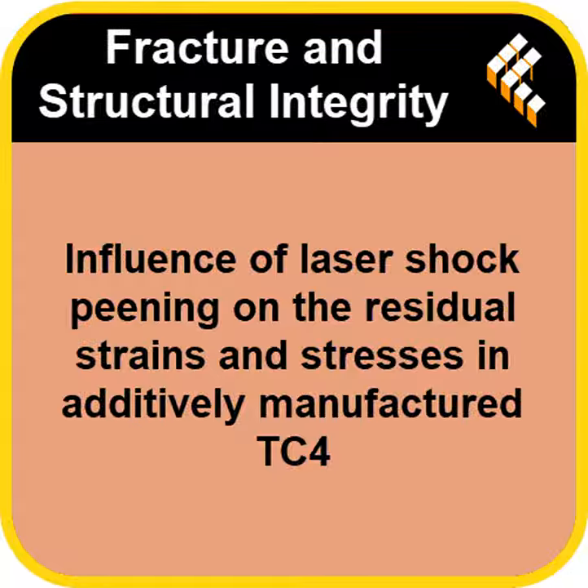This sounds less like manufacturing, more like science fiction. How does a laser pulse create enough force to reshape metal internally? It's all about controlled plasma generation. It's a neat chain reaction. You need a few things. First, you coat the titanium surface with something called an ablative layer. Like a sacrificial coating? Exactly. Could be black paint, maybe metallic foil, PVC tape even, something to absorb the laser energy.